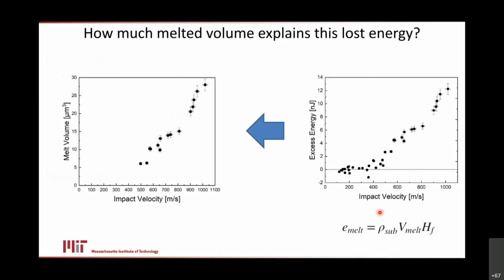This is the maximum amount of stuff we might have melted at all these different velocities. At our highest velocity, we might have melted up to 30 cubic microns. All right, so that's an expectation now. By the way, in copper, when I was talking about jets in copper, we were talking about 1 cubic micron. Those jets are teeny tiny. This is a giant splash. 30 cubic microns of material could have melted with this energy budget.